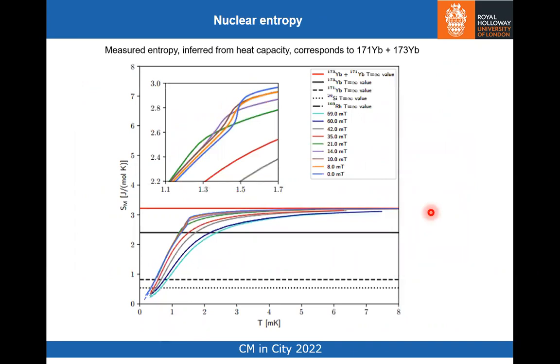This heat capacity that we're measuring, we measure it from 0 millitesla up to 69 millitesla. So we measure it to beyond the in-plane quantum critical field. And before I show you the details of that, I just want to be clear about what the origin of it is. With all of this data, if we integrate the heat capacity, what we get to some pretty high degree of precision is the total nuclear spin entropy of 171 and 173 ytterbium. So it's clear that we're measuring the nuclear spins here.